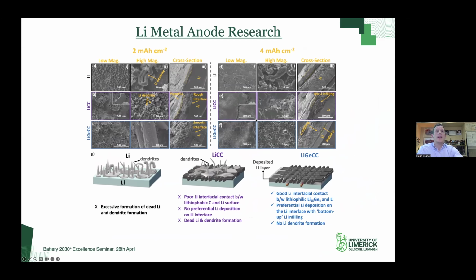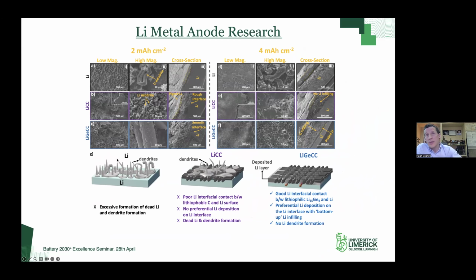So looking then at the ex situ analysis of this, you can see the summary of it is down here at the bottom. When we have just lithium on its own, these are across the top column that you'll see here. And these are the characteristic filament type growth that we see for lithium up here at the top. Okay, so this is your cross section. This is at 2 milliamp hour per centimeter squared. You see that this interface between the freshly deposited lithium and the old lithium is disconnected in the first place. And here it's even more pronounced once you move to 4 milliamp hour per centimeter squared. Okay, so that would explain why we saw significant capacity degradation in the case of the control lithium.